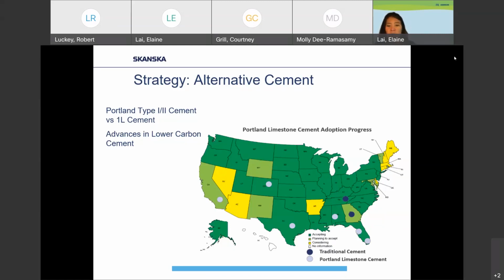In general, when projects are using this type of cement, the 1L cement, you're seeing an approximate 10% reduction in the GWP. So GWP stands for global warming potential. That's the key measure of carbon intensity. So you're seeing an approximate 10% reduction in GWP for mix designs that use 1L in lieu of traditional type 1-2 cement. This map that you see is a map of the growing number of states where the State Department of Transportation has either accepted or is currently considering accepting the use of type 1L cement on DOT projects.